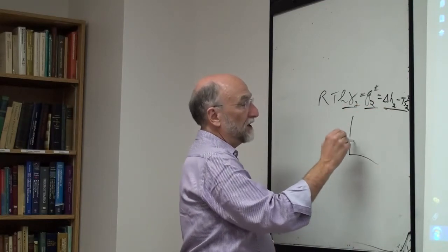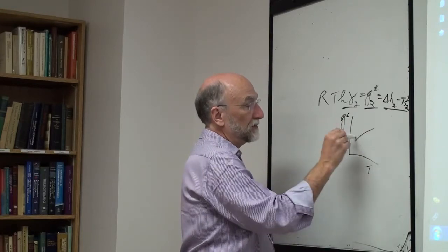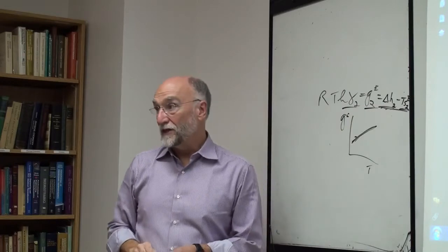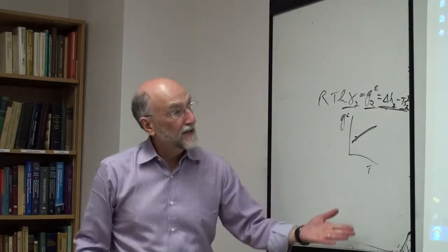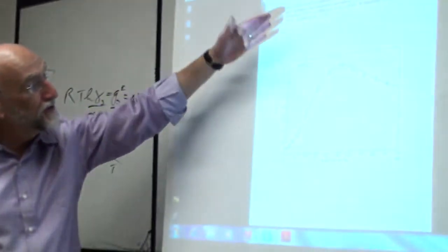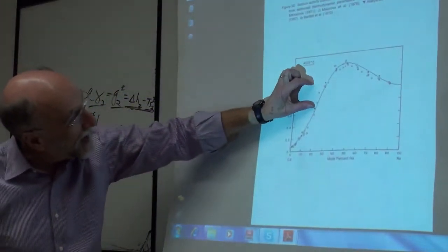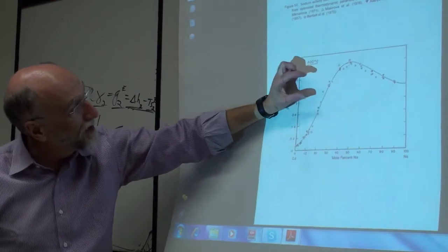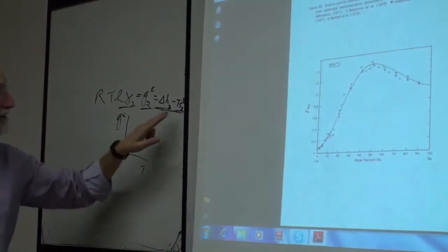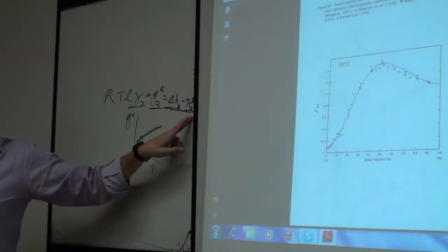So we fitted RT log gamma, we fitted GXS2 as a function of temperature, and from the slope you can get the partial heat of the excess entropy. But that's even less accurate, because if you measure this from 400 to 450 degrees, maybe your log gamma is quite accurate, but since you only get such a small temperature difference, a slight error can have a huge difference in the slope, okay?